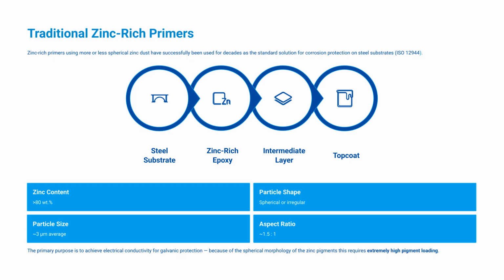The purpose of this very high zinc loading is to create electrical conductivity throughout the coating. Because spherical particles only touch at relatively small contact points, a very high pigment concentration is required to establish an effective conductive network. This high zinc content delivers galvanic protection, but it also introduces formulation and application limitations.